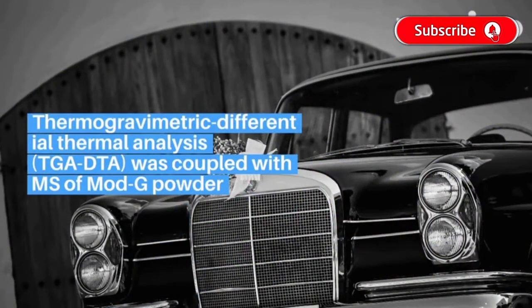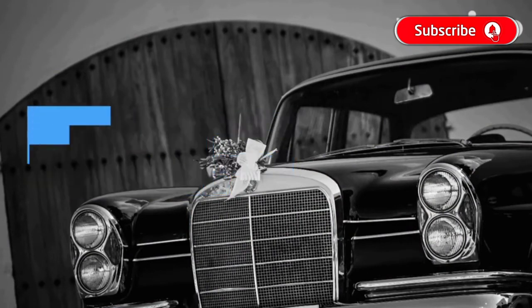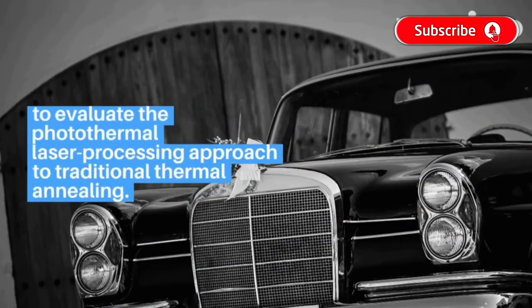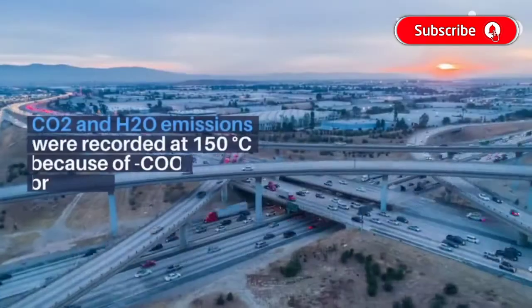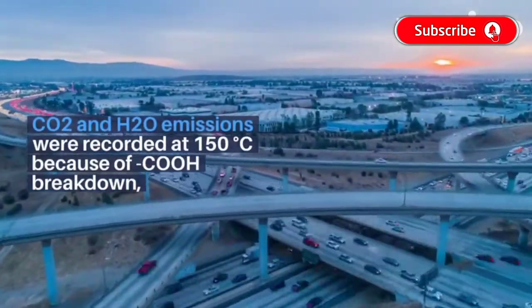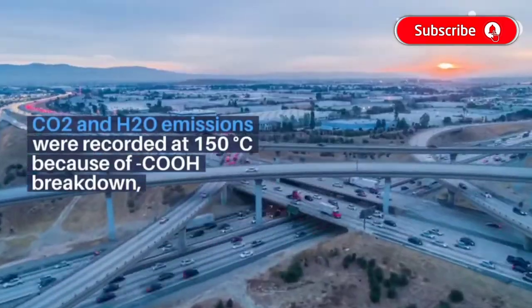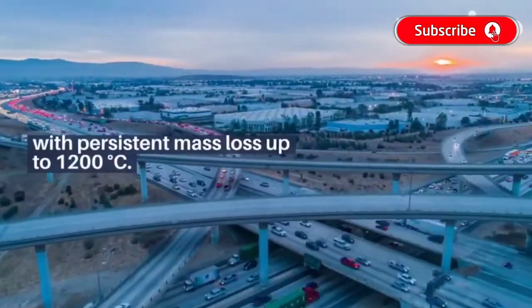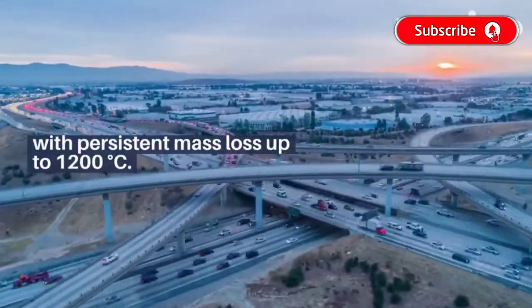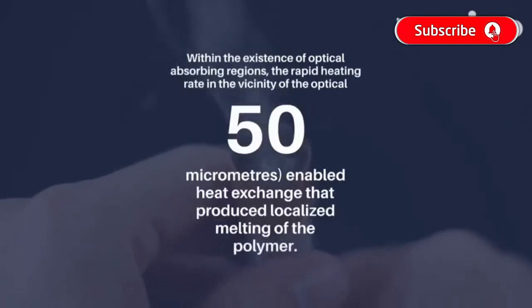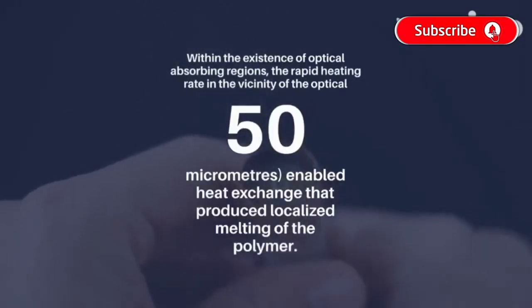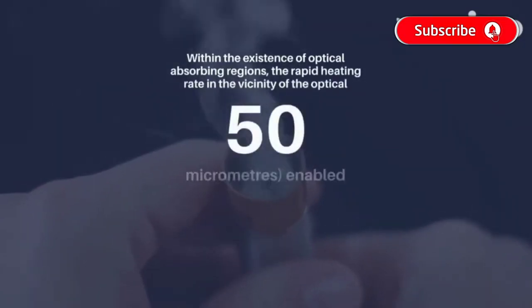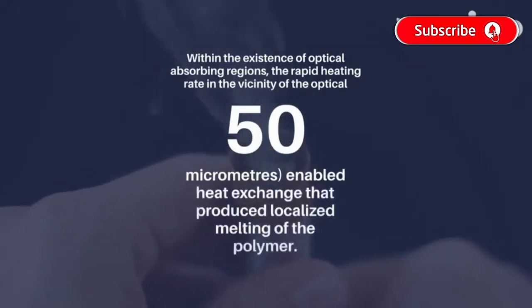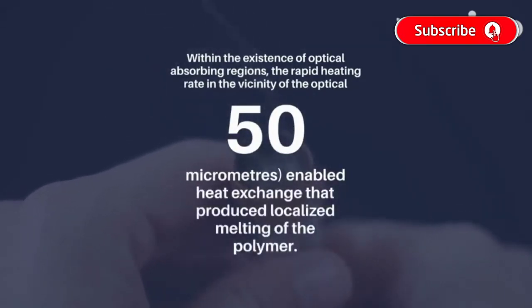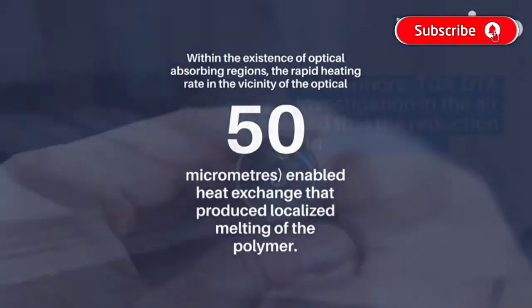Thermogravimetric differential thermal analysis was coupled with MS of Mod-G powder to evaluate the photothermal laser processing approach against traditional thermal annealing. CO2 and H2O emissions were recorded at 150 degrees Celsius because of COOH breakdown, with persistent mass loss up to 1,200 degrees Celsius. Within the existence of optical absorbing regions, the rapid heating rate in the vicinity of the optical beam size enabled heat exchange that produced localized melting of the polymer.